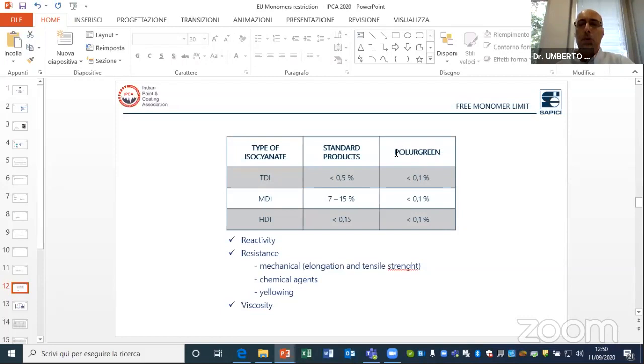Sapici has developed the polyurethane line where the level of free monomer is below 0.1%. Speaking about the MDI market, normally standard products have a content of free monomer from 7 to 15%, and we developed a product with a content of free MDI that is inferior to 0.1%. Speaking about HDI, we have a standard product with a monomer content of 0.15. And today with the polyurethane line, we have products with free monomer content below 0.1.